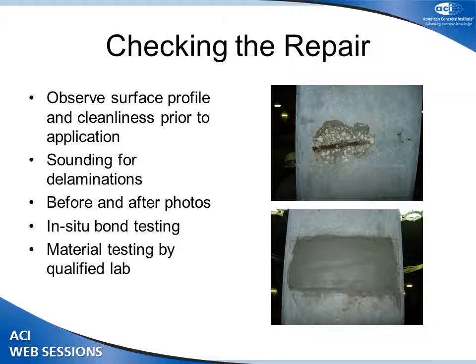Bond testing is also possible. There are guidelines to do pull-off testing, where you're coring into the material, slightly into the base concrete, and pulling off and determining the bond strength, but also where the failure mechanism is. Did the bond exceed the tensile strength of the concrete is one of the criteria. This type of testing would commonly be done by an independent materials laboratory. And that's repair application procedure number 6, vertical and overhead repair.